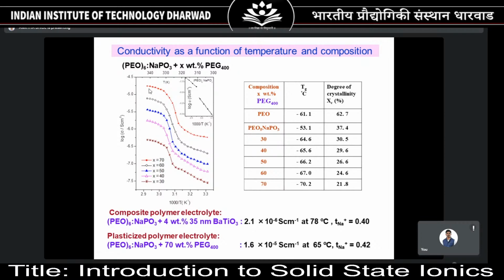That means here we could not add a further amount of polyethylene glycol, because the original structure, what we want, a freestanding polymer electrolyte, is lost since it has more liquid content. You cannot peel it off, or you cannot take it as a freestanding polymer electrolyte. Therefore, we have to limit the content of polyethylene glycol up to 70%. And you could get the enhancement in conductivity of the order of 10 to the power minus 5